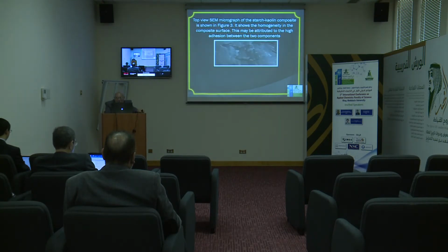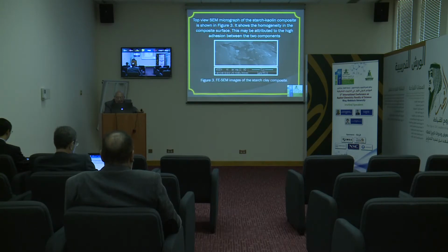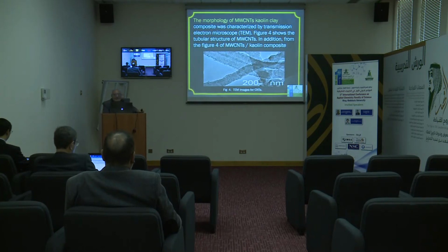The interpretation of such structures depends upon the disappearance of the parent peaks and the appearance of new ones, so that the new composite has been elucidated. A top view SEM micrograph of the starch kaolin composite is shown in the figure. It shows homogeneity in the composite surface, which may be attributed to the high adhesion between the two components. For this sake, starch has been selected.